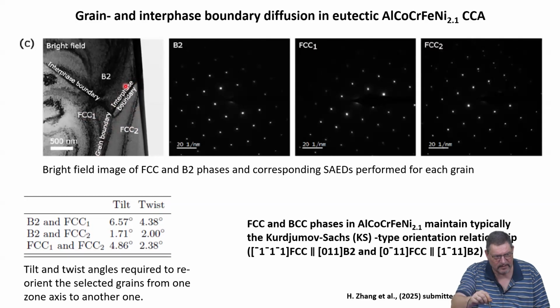When we look at these electron diffraction patterns, which you see here, so selected area electron diffraction, you can see nicely B2 and FCC patterns. Not always nicely resolved because some of the misorientation with respect to the direction of the incident electron beam are such that you do not see all the reflections. When you analyze them, then you see that we have preferentially an orientation relationship known as Kurdjumov-Sachs, KS orientation relationship. Do you know what an orientation relationship means?